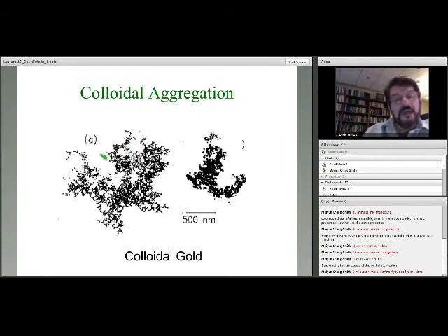Notice here you can, in many cases, not really see through this object. Here, of course, there's a hole, but here it's much more dense. And since this is a projection, you can immediately say, well, because it's essentially as dense as space, the fractal dimension is going to be something between 2 and 3. It's going to be greater than 2 because I'm looking at a projection and I can no longer see through it. There's a very distinct difference between these two.